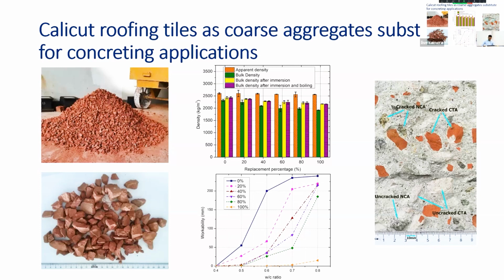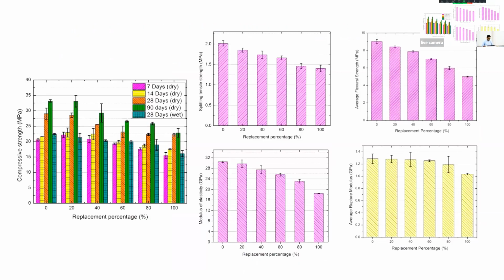The corner figure shows the crack surface of concretes. As you can see, the normal concrete also cracks. The normal aggregates also crack, and in addition to that, calicut tile also shows cracks. But when you compare the fraction between the normal aggregates and calicut tile aggregates, calicut tile aggregate shows higher fraction, because the mechanical properties of calicut tile aggregate are a bit low compared to normal aggregates. But anyhow, we can use these calicut tile aggregates up to some level, nearly up to 40%, without a significant change of the properties.